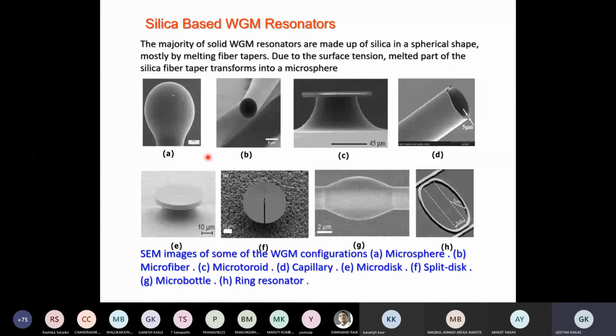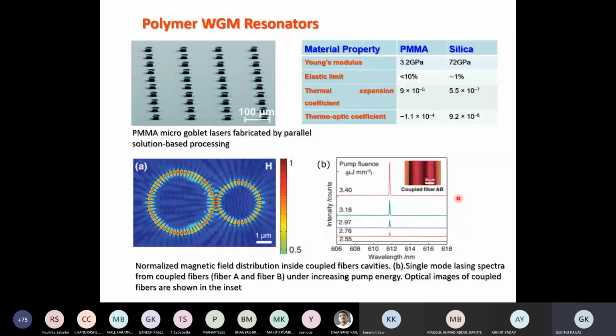So these are various examples of microspheres, microfiber, microtoroid, capillary, then microdisc, split disc, microbottle, and ring resonators. So you can create a large number of polymer WGM resonators. If you come to polymer, we have discussed glass, and now you can see that if you make use of polymer, it is very easy, because the temperature requirement is very small in polymer. That is, it requires only 200 degrees for your processing, unlike 2000 degrees for the glass. So a large number of microgoblet lasers fabricated by parallel solution processing method, a large number of such microstructures based on PMMA polymer is shown here.